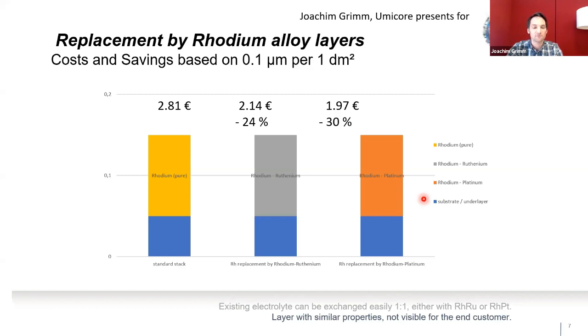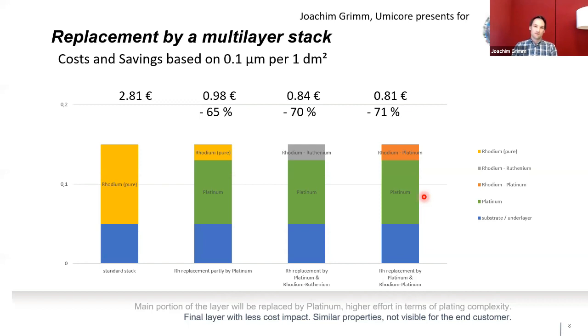Okay, but coming to level number 2. Why do a pure rhodium layer on sterling silver? Your client wants to have something white, shiny, like he's used to from the rhodium plating. So we give him the rhodium plating on top. But platinum is a precious metal as well, has a high hardness and corrosion resistance. So it's the same category of precious metal that your client likes to have. And if you see the same thickness on the whole sequence of plating, you can do an intermediate layer of platinum and just a pure rhodium plating on top. And you get in the final end 0.1 micron of precious metal white platinum layer.